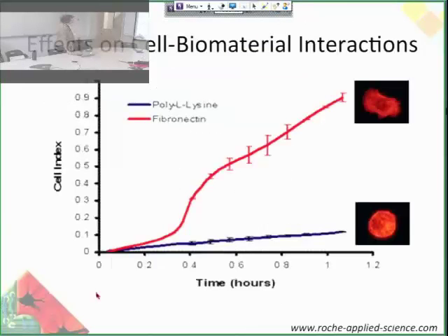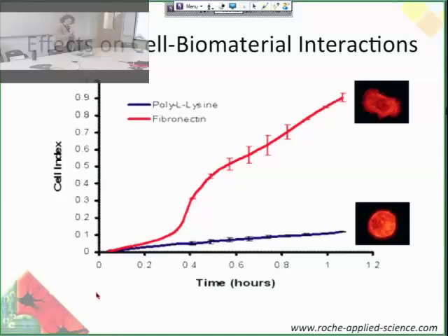In a similar study, you could either coat a glass slide with polylysine — a charged protein polymer — and you have very low cell attachment; the cell is rounded up and not really attached, looking like a water droplet not spread on the surface. But if you first coat the surface with fibronectin, the cell can attach and spread out a little bit. The spreading is a really good indication of whether or not the cell is attached.